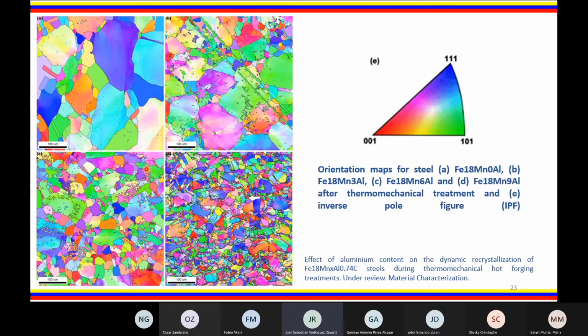In this figure, crystallographic orientation maps of the thermomechanically treated FeMnAlC samples are represented. The microstructure of the material does not result in preferential orientation. In contrast, the arrangement of the grains with respect to the crystallographic direction was completely random.